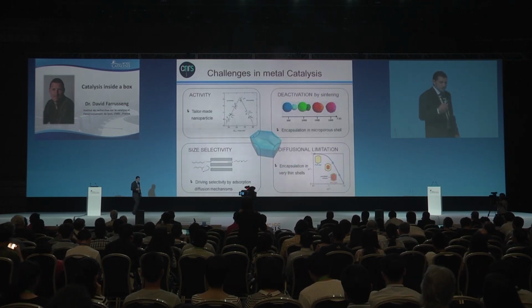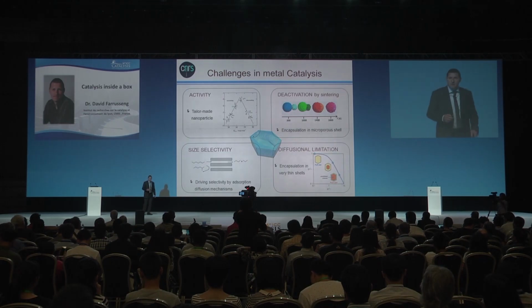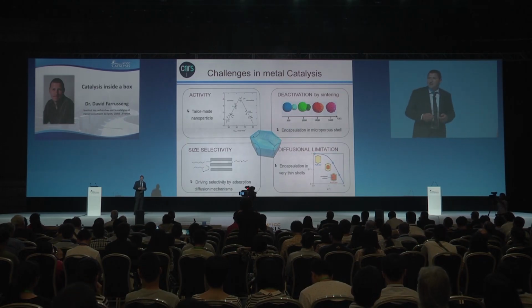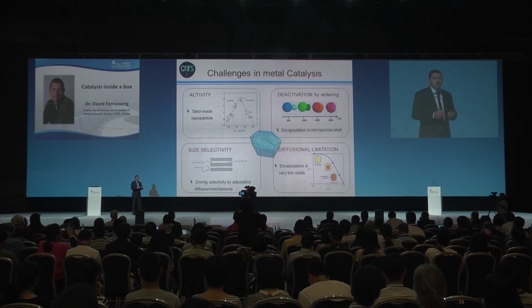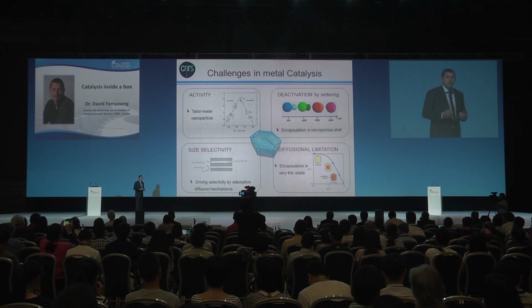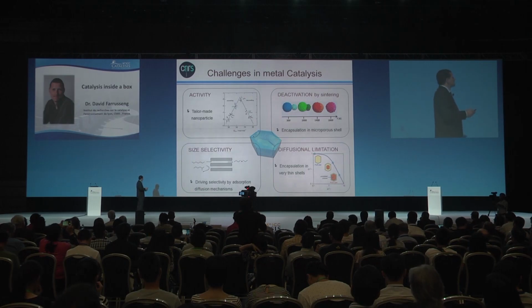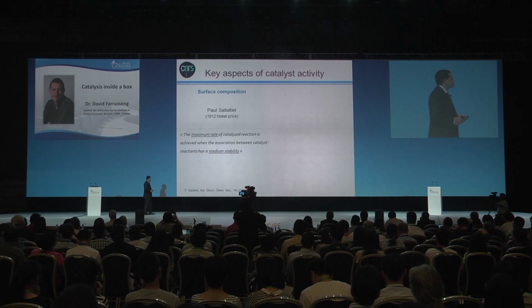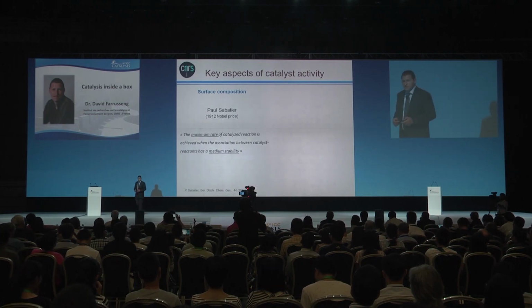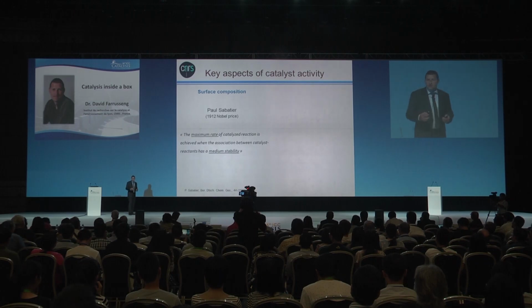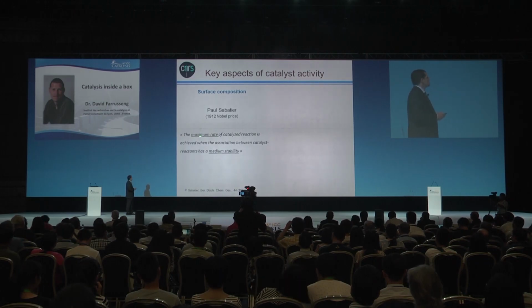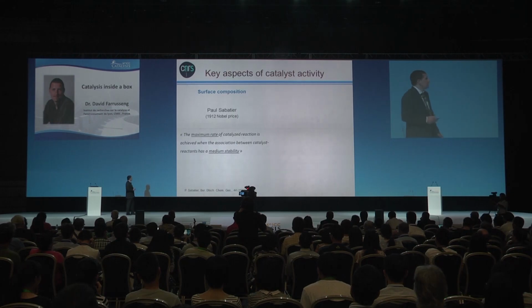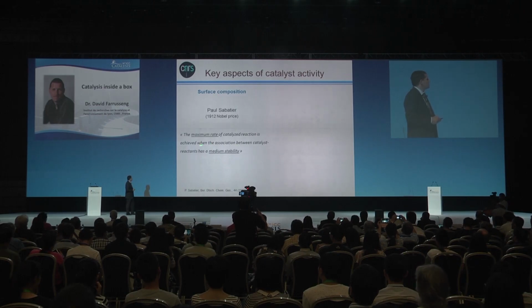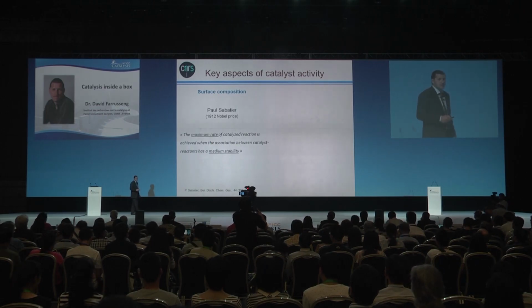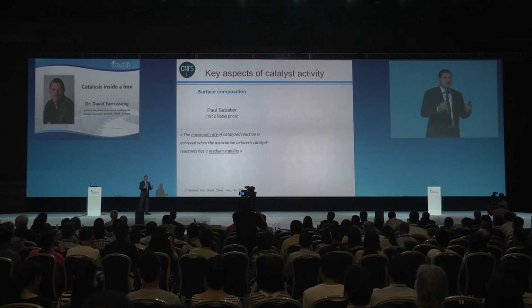So now with this, let's say, nano vessel, I will show you how we can make the nanoparticles and how we can control the surface composition and also the size of the particles. And I would like to give you first why we want to do that. It's important, of course, in metal catalysis to control the surface composition, because, as Paul Sabatier said, the maximum rate of the catalyzed reactions is achieved when the association between catalyst and reactants has a medium stability. So it's important to design the catalyst well beforehand.